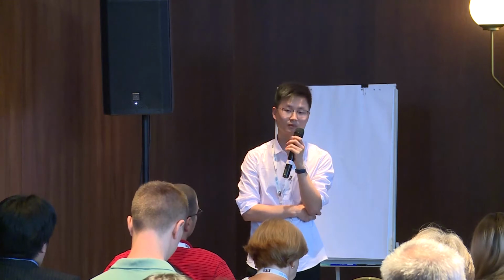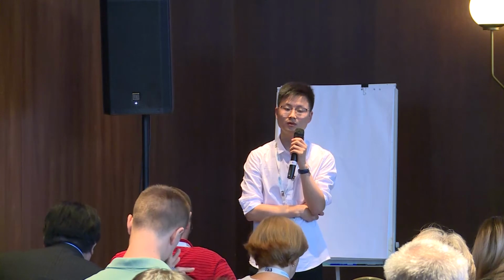Are there further questions? Thank you for your nice presentation. Just a question, please. The specimens were tested as given by the company, or did you change some parameters of the manufacturing procedure? Because I have done the tests that you showed in the same alloy, and I have no microporosity at all, because we have optimized the parameters with which the specimens are produced. So the first thing is to optimize the parameters for fatigue life, and then you can test other things. So it's not only to check what they give us, but the better way is to first of all get the best specimens. That's my opinion.